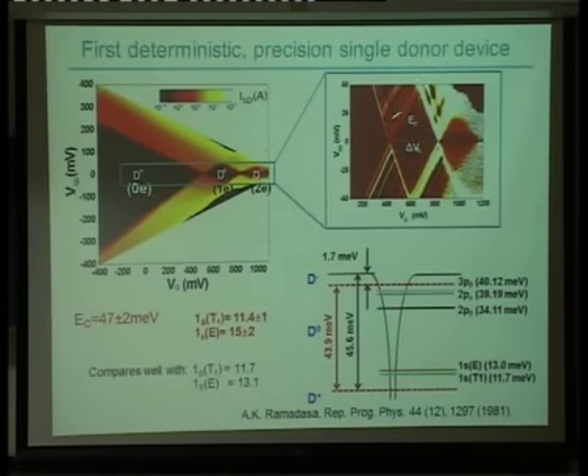The other thing is you can actually look at the excited states here. They're mixed in with the one-dimensional density of states that I talked about before. And again, you find that the excited state energy levels match. But I guess one of the key things you can see here is if you look at zero gate bias, the donor is already ionized. So you have to go to about 450 millivolts to actually get the electron to sit on the phosphorus atom.